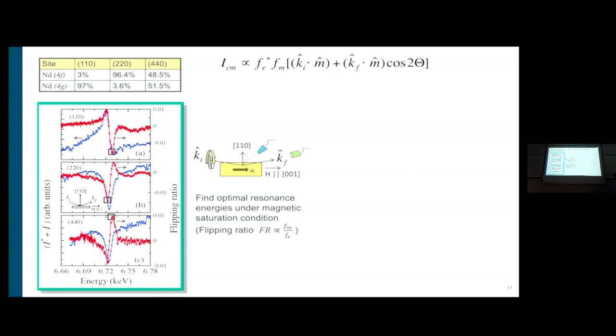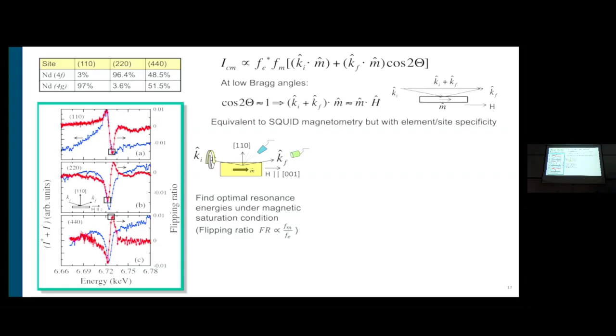And the red is the difference in the Bragg intensity for left and right helicities. So you see this is about 1%. This is the gain we got in this 1% charge magnetic interference. So this red signal is sensitive to only one type of neodymium atom, here, the other one, or both. And one interesting point here is that if you look at this geometric factor that has sensitivity to the direction of the magnetization, you can immediately see that if you reverse the magnetization, it changes sign.